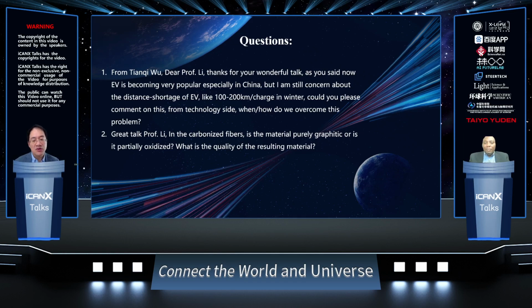Now, of course, when we try to use this system, try to make electrodes, we also need some electronic conductivity. So there needs to be a balance between how dirty it is on the surface, and how good an electronic conductor it is. But for the active catalysis, for this extreme processing, we actually need to have pretty dirty carbonized fibers.